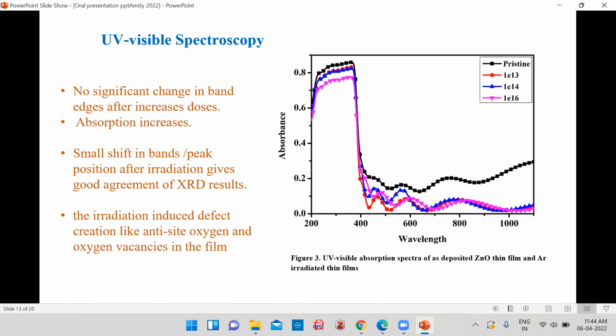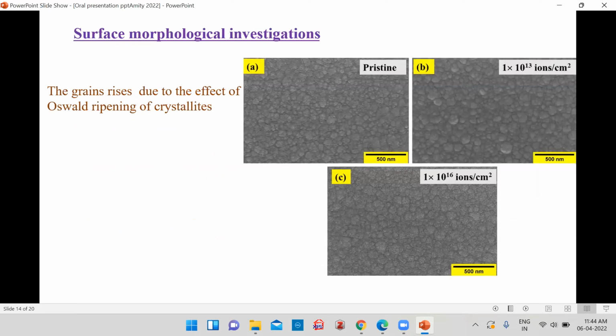This increase in the absorption reveals the irradiation induced defects creation, like anti-site oxygen and oxygen vacancies in the film. These are the surface morphological investigations, in which we can see that after irradiation there are very small grain rises in the images, due to the Ostwald ripening of crystallites.